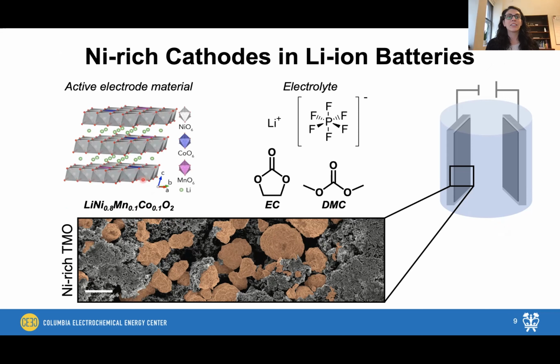This is a layered material where you have your transition metal oxide layers, and your lithium intercalates in between these layers, and intercalates and deintercalates during charge and discharge of the battery. The liquid electrolyte that we're going to be using in this system, the salt that we're concerned with today is LiPF6. And the solvent is a 1-to-1 mixture of ethylene carbonate and dimethyl carbonate, so both a cyclic and a linear carbonate molecule making up our solution here.